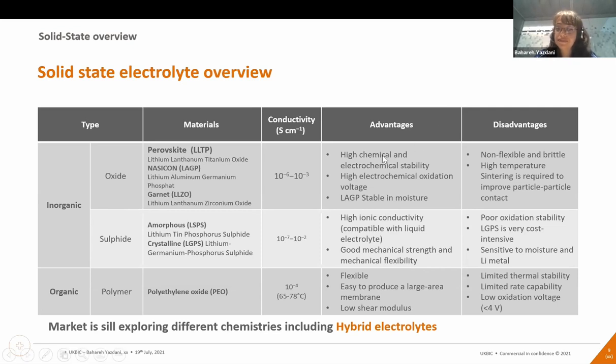So oxides have a little bit lower level of ionic conductivity compared to the sulfide base. However, they have better chemical and electrochemical resistance, and a larger electrochemical voltage window. And some of their types, for example LAGP, which is a NASICON-type electrolyte, are resistant to moisture, so it can reduce the manufacturing cost and is more compatible for scalability. And of course, they have a disadvantage because they are brittle, non-flexible material, and they also require high temperature sintering for better particle contact, which increases their cost.